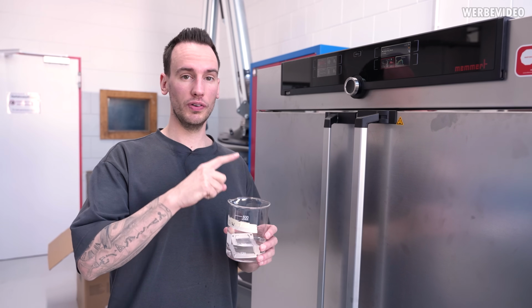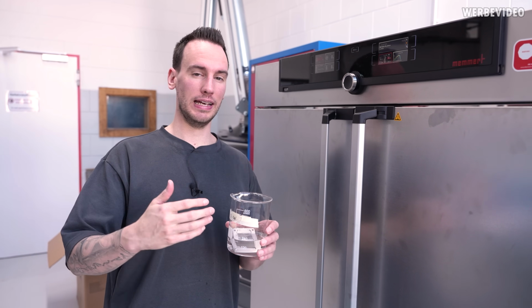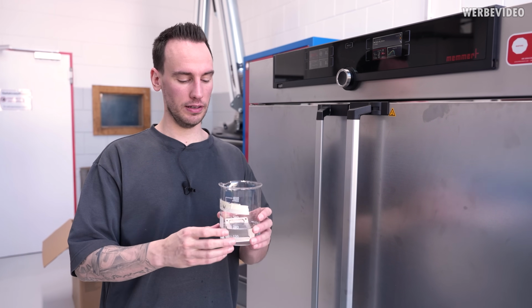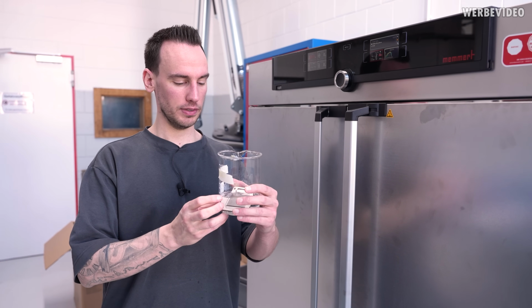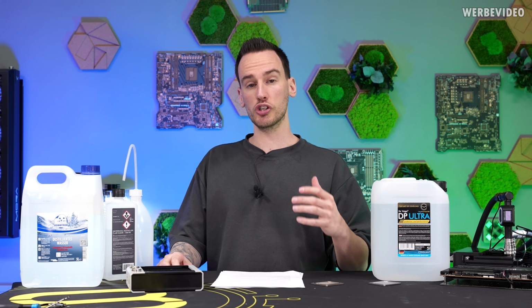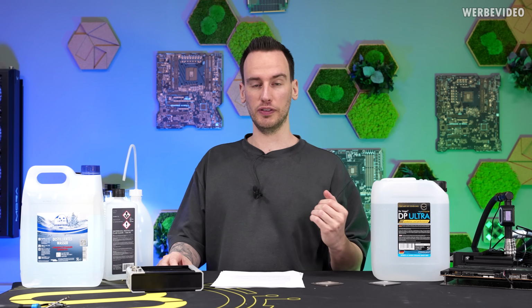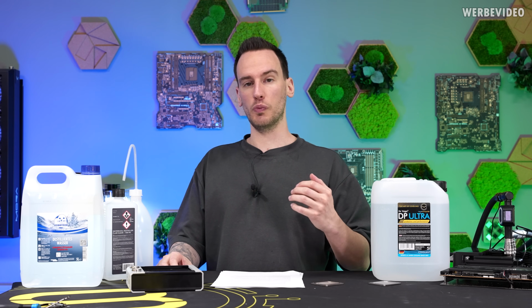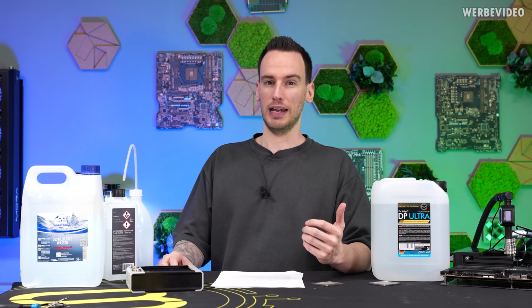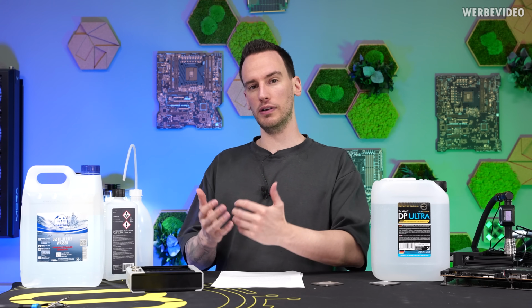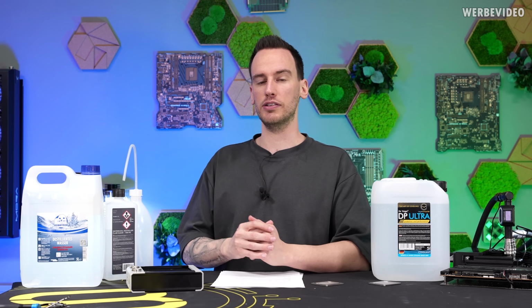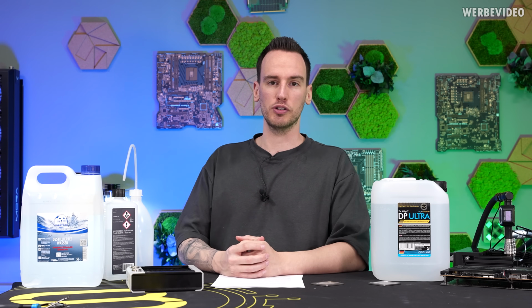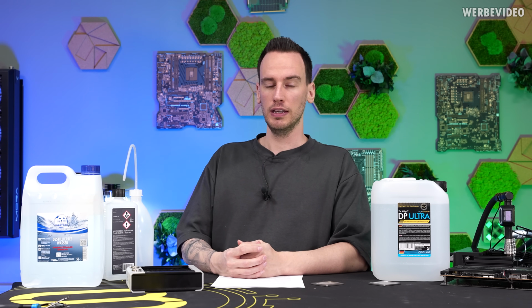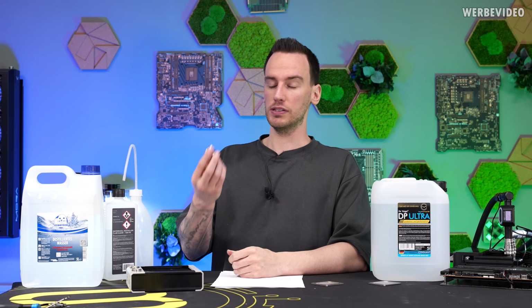We're now putting this into an oven at 60 degrees Celsius, because at a higher temperature, it's also accelerating the aging a little bit and just saves us time testing. Corrosion in a water cooling loop will depend on a lot of different factors, but it starts with the materials that are being used. And most people just have their copper cooler and copper radiator in mind, and then they're like, yeah, I'm just using the same material for everything. But it's just a lot more complicated, starting with the fitting.